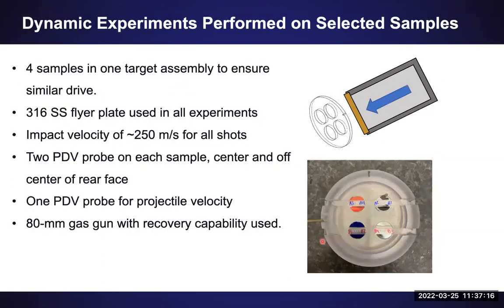What some of the experimental setup looks like is we want to make sure that most of the samples see the same loading conditions, because the only thing we want to change is the microstructure. To ensure that, we put multiple samples in an assembly. So here at the bottom, the colored regions are the samples. There are 4 samples in this assembly. The PDV probes go in these holes. And in this experiment, we were using 316 stainless steel for our samples, for our impactors, and also for these momentum rings around the sample to prevent lateral release waves from coming in.